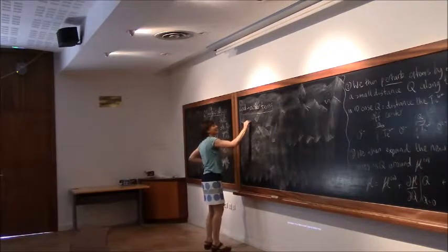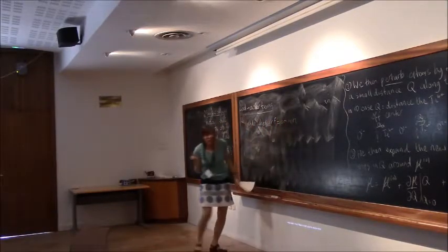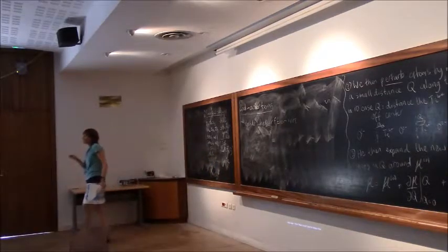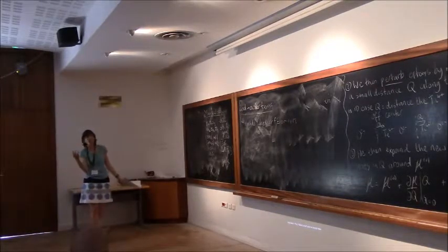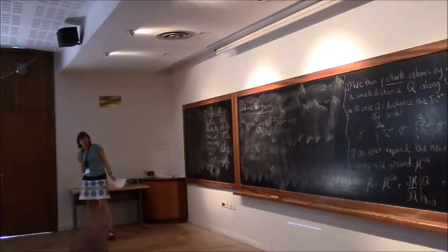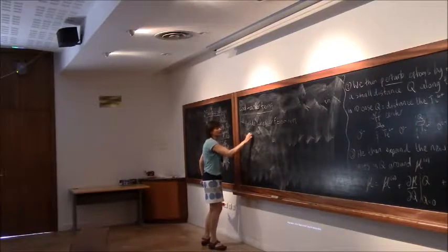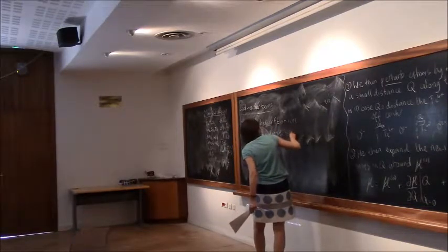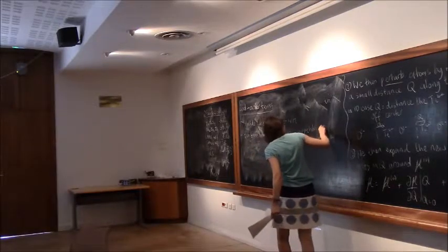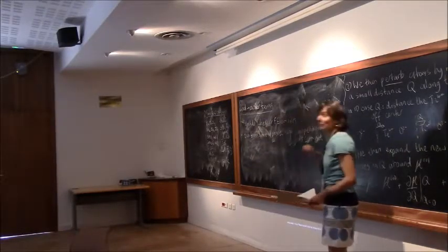So these decide whether my system is ferroelectric or not. So the first thing to notice is they have opposite signs. So whether something is ferroelectric or not is a competition between these two terms. It's not a fundamental symmetry requirement like the first order Jahn-Teller effect. In the first order Jahn-Teller effect we have only one term. It's 0 or not. So whether something's going to be ferroelectric or not is a competition between two terms. The two terms have opposite sign, and their competition decides whether something's ferroelectric. The first term is bad for ferroelectricity, the second term is good.